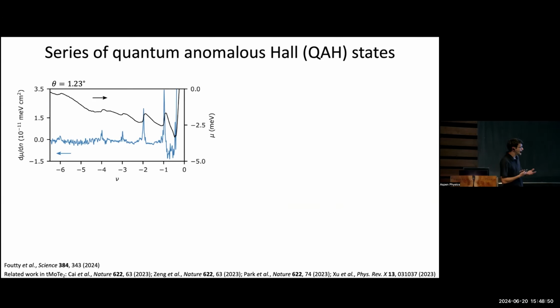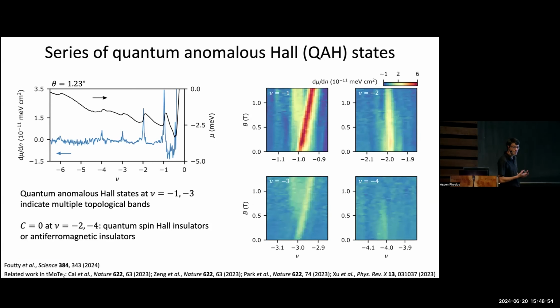And in order to tell what is the nature of the insulating state that develops, what we do is we apply a magnetic field, just track how it evolves as a function of magnetic field. Any topological state should be sloped in magnetic field like the Hofstadter states. And indeed, if we look at nu equals minus 1, as we increase the magnetic field, there's an incompressible peak. Sorry for the change in color scale. Red here corresponds to incompressible. It goes all the way down to zero magnetic field with a slope. This is a quantum anomalous Hall state, like I talked about at the introduction.